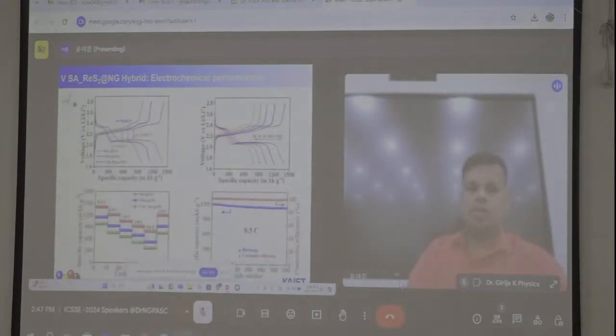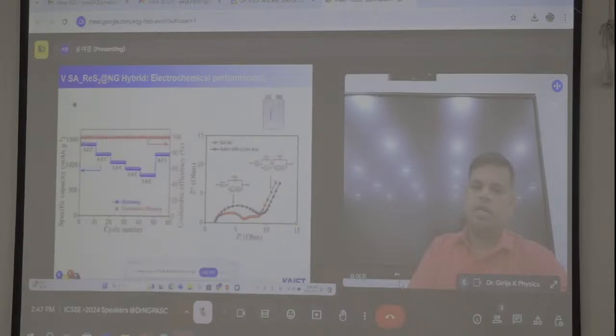I also do the charge discharge process. You can see the specific capacity of our optimal catalyst is higher compared to the other catalysts, and the rate performance at different current densities shows higher specific capacity and high reproducibility after high current density. When increasing the current density from 0.2 C to 5 C, the charging discharging is almost retained, and for durability over 600 cycles there is not much loss, and the coulombic efficiency is almost near 99.95%.